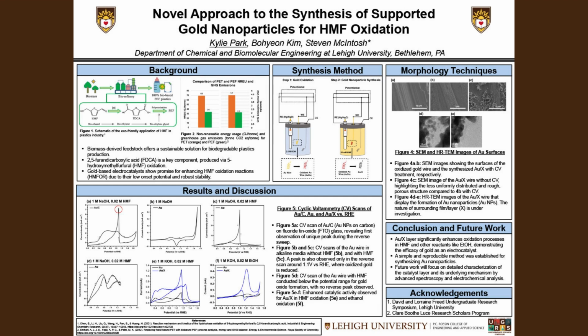Figure 5d is a CV scan of gold with HMF below the potential range for gold oxide formation. The absence of the reverse peak confirms that the peak in 5c is related to the reduction of the oxidized gold species. Leveraging the strong interaction between reduced gold oxide and HMF oxidation, we modified the electrode to enhance and stabilize its catalytic activity. And so we developed a simple synthesis method that consists of 2 steps: gold oxidation and gold nanoparticle synthesis.